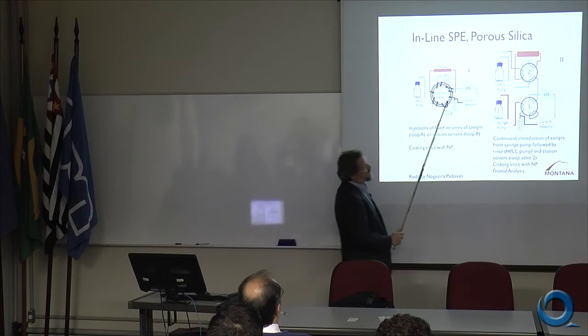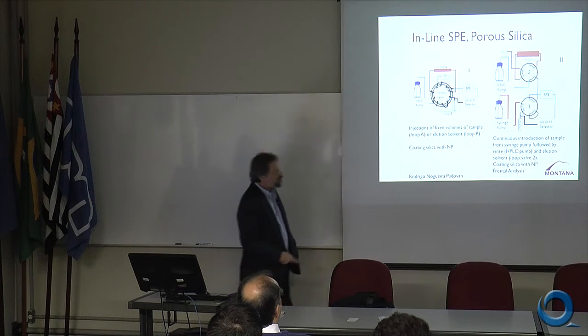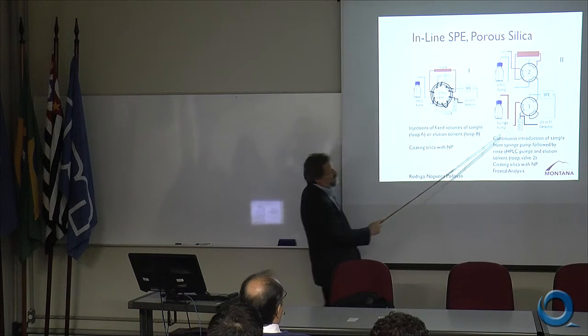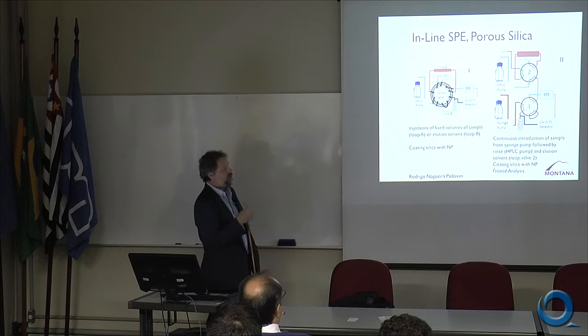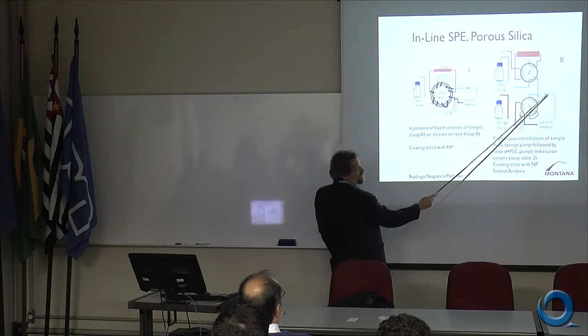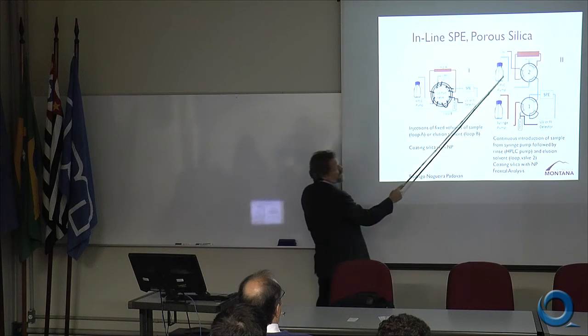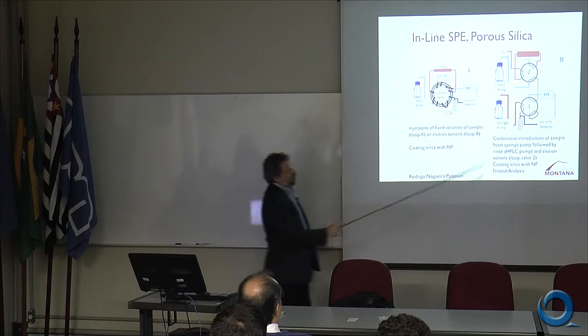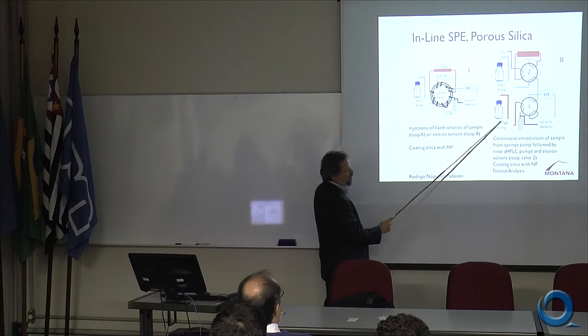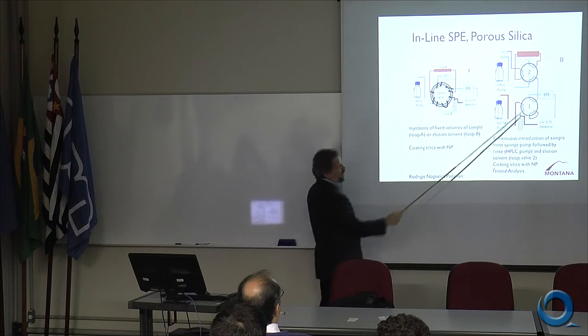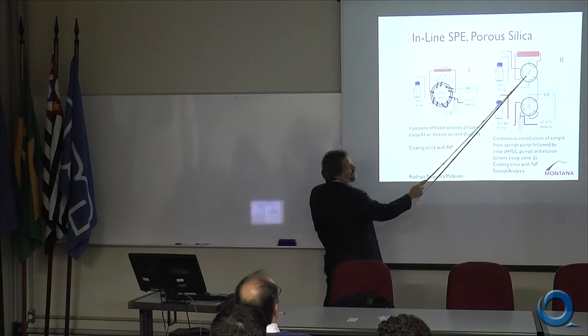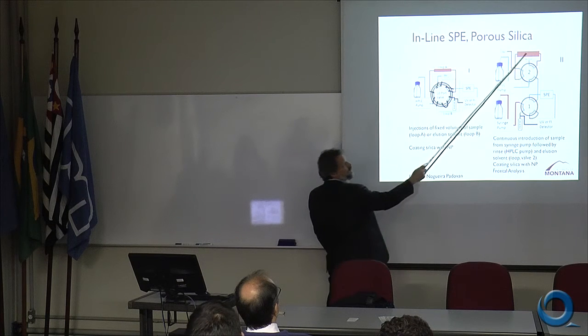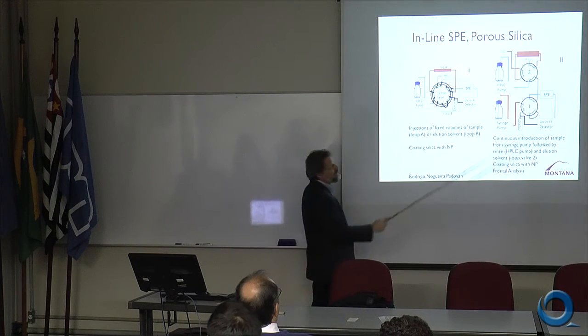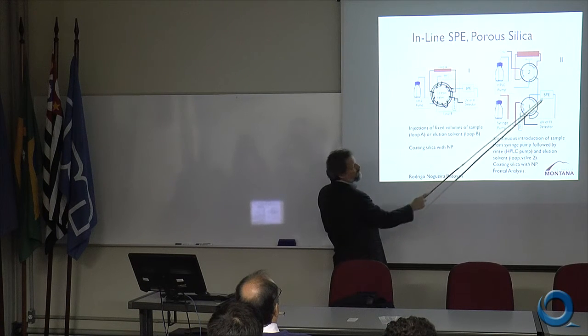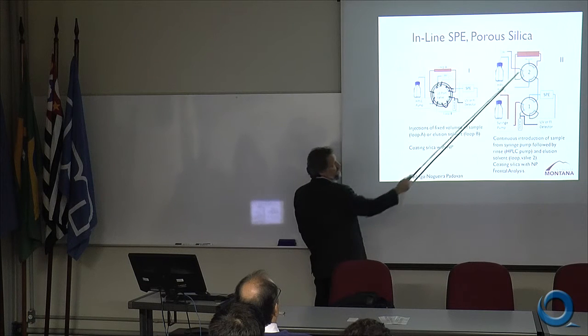This worked out reasonably well, but we moved on pretty quickly to this system where we're using a syringe pump to continuously introduce our sample solution onto the solid phase extraction column. So we have an HPLC pump pumping a solvent, a mobile phase. We can switch this valve to where now we're pumping our analyte solution onto the solid phase extraction cartridge. Still have a detector after the column. And then we have a second injection valve in here where we can inject our elution solvent. So we can inject small volumes of elution solvent after we have loaded the column with our analyte. We can then elute it using this elution solvent.